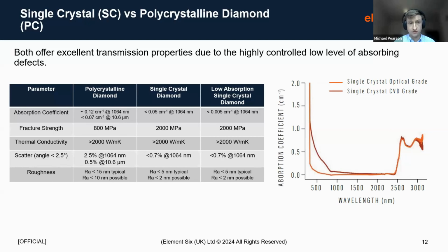So single crystal diamond, we're able to achieve surface finishes of less than 2 nanometers Ra. So very, very smooth surfaces. Polycrystalline material, we're still achieving very, very smooth surfaces, but typically we're able to achieve less than 10 nanometers at a sort of best effort on an optical grade polish.